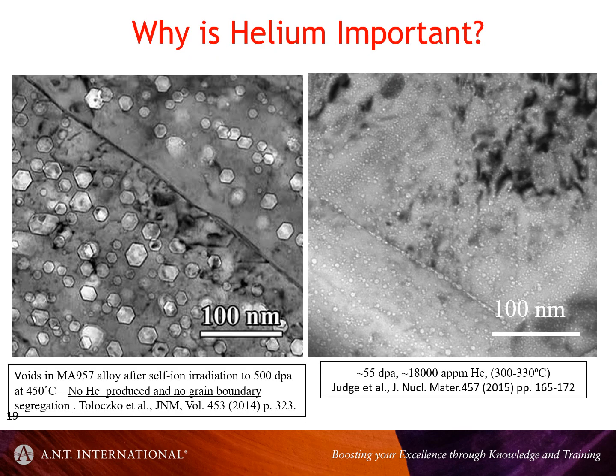why is this important? Well, it's important because if you have a material which is swelling like this, this is from a self-ion irradiation, where you get lots of swelling for whatever reason. We don't have to understand why. Typically, the boundaries are bubble-free or cavity-free, void-free, I should say, and that's because vacancies are simply absorbed by the boundary, and then they can diffuse or combine. You don't get cavities segregating on the boundary when there's no helium there, but when there is helium there, you do. You get lots of segregation, and that is one of the features of helium.